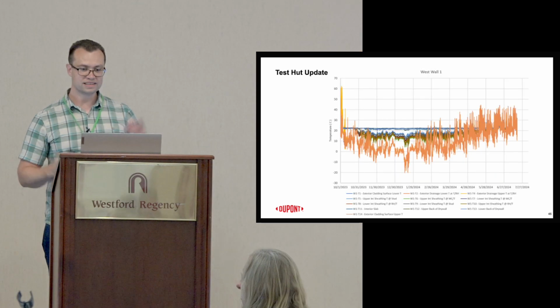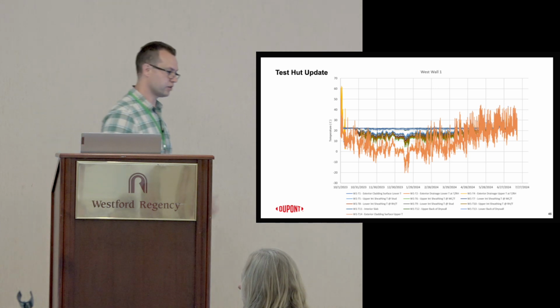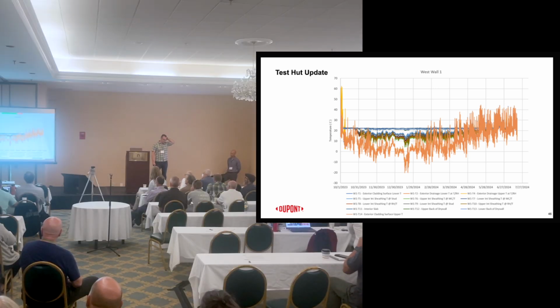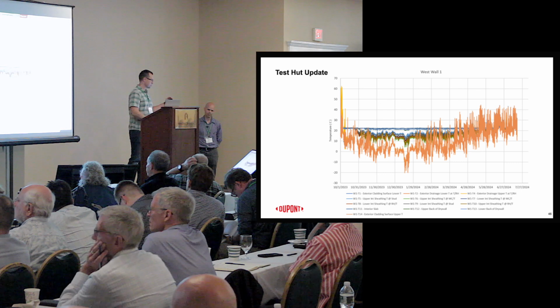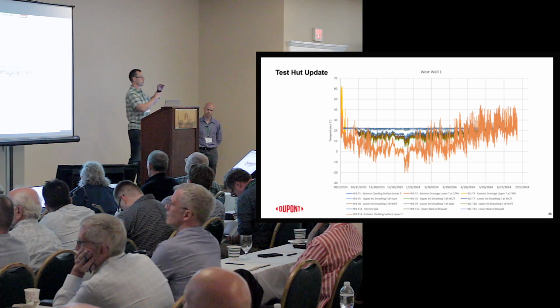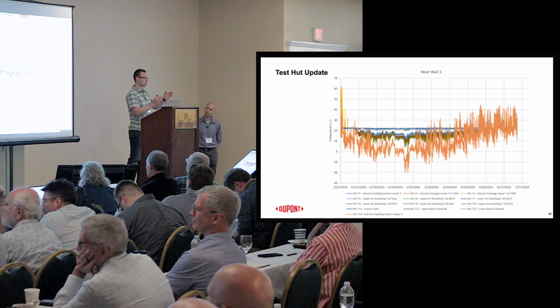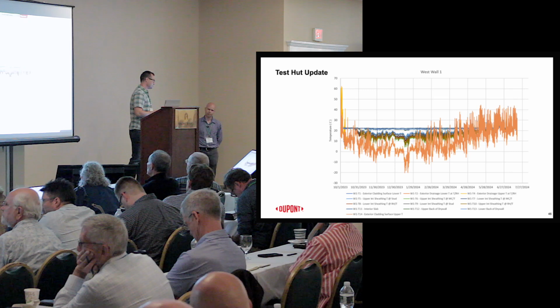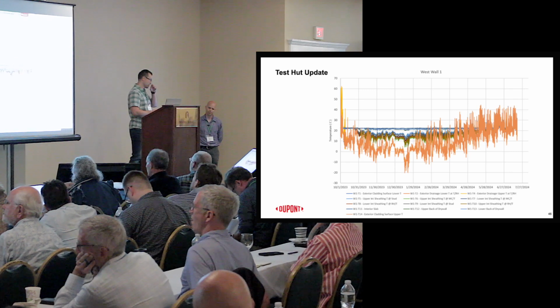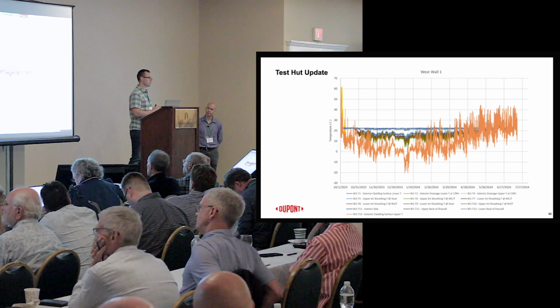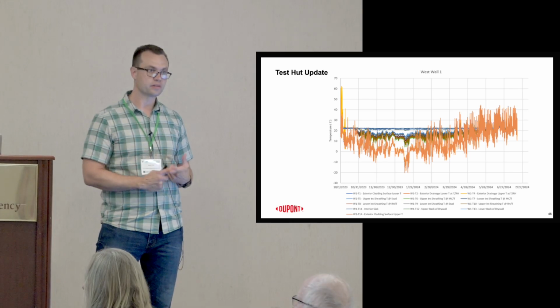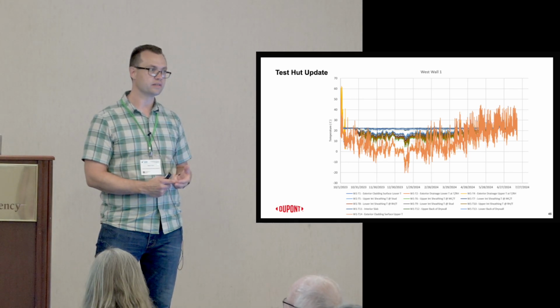And then, what does that mean? So that's a graph, and this is the level of data that we get from every wall, and that's from when it started up in October. You can see in early October, the temperatures start to split and separate. That's because we actually got the insulation in the walls. So the sensors were getting cooler and cooler on the outside. And then that, like 14 sensors, that's just the temperature data for every wall. We also have relative humidity data and moisture content data for everything.